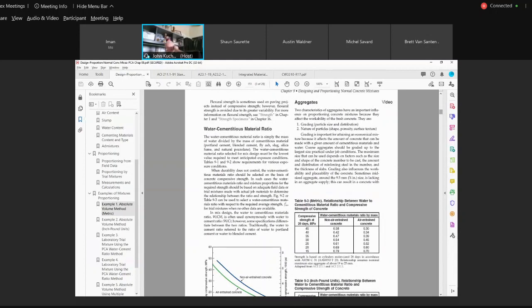If we go to table 9.3, like I stated, compressive strength at 28 days, 32 MPa is in between 30 and 35. We're not non-air entrained, we're air entrained. So we're between 0.39 and 0.45. Well, if you extrapolate it, 32 is not quite halfway. It's actually 32 and a half, but it still works out to a difference of 6, add 3, 0.42 water cement ratio for 32 MPa concrete.